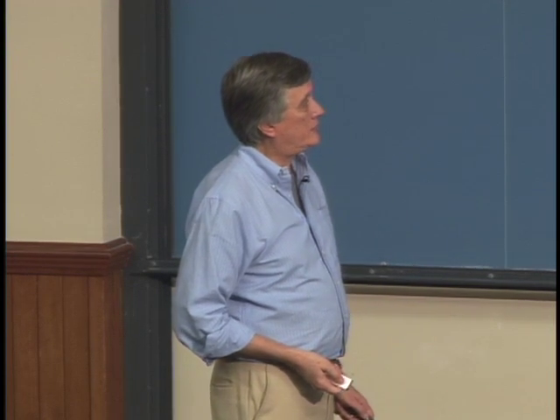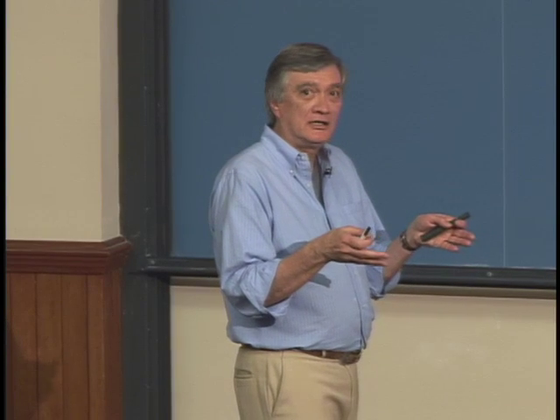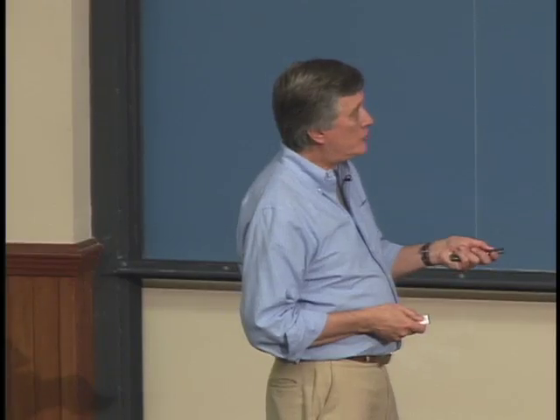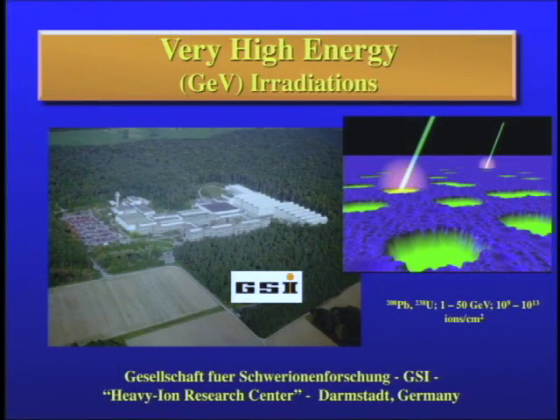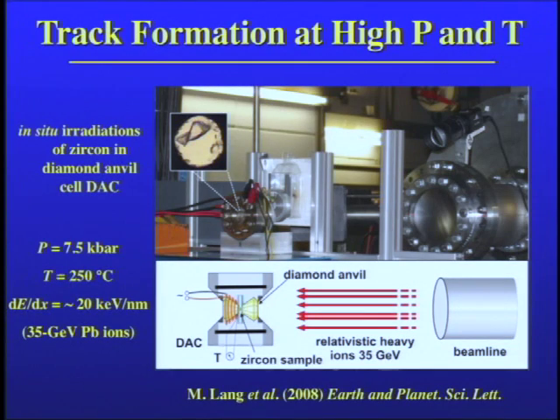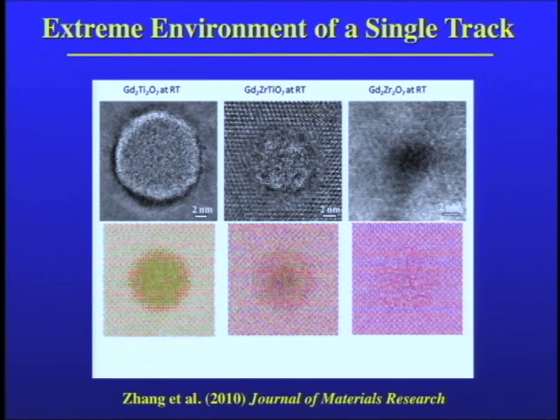The other thing we've begun to do is move out of, I would say, small bits of damage and use very high energy ions, maybe 50 GeV ions. We do our experiments in Germany. There are only 2 accelerators in the world, one in Russia at Dubna, the GSI accelerator in Germany. The Chinese will have the next. There's none in the United States, but we can do very high energy irradiations, and what's important is the energies are high enough to drive the ions through the diamond cell, through the diamonds, and into the sample. Okay? So we can combine high pressures with high energy deposition. In this case, this is the rig looking at zircons, and we get the damaged tracks.